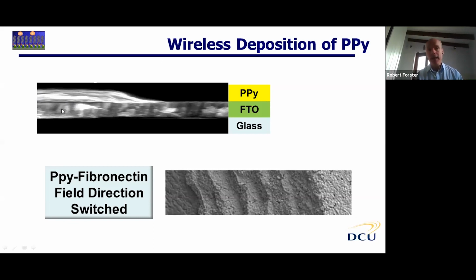What you're looking at here is the underlying glass substrate, about 100 nanometer thick layer of fluorine doped tin oxide, and then on top of that, down at this end of the electrode, about a 100 nanometer thick polypyrrole layer. On the other end of the electrode, which remained at a reducing potential, you don't see polypyrrole deposition because we're not oxidizing the monomer and therefore driving the formation of the film.